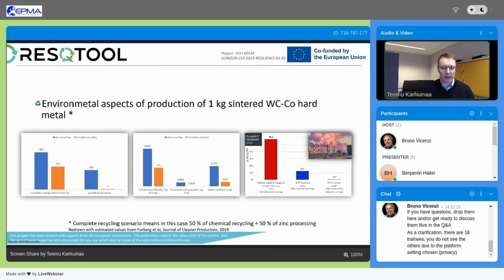The recycling plays a big role here. And we published in the last Plansee Seminar, on the right side, the figure of what the CO2 emissions are for production of 1 kilo, in this case raw material, tungsten carbide. And there are articles available on the internet that according to one study, for Chinese tungsten carbide production with mainly coal-fired electricity and 90% virgin raw material, it can be as high as 60 kilos of CO2 equivalent per kilo of tungsten carbide powder.